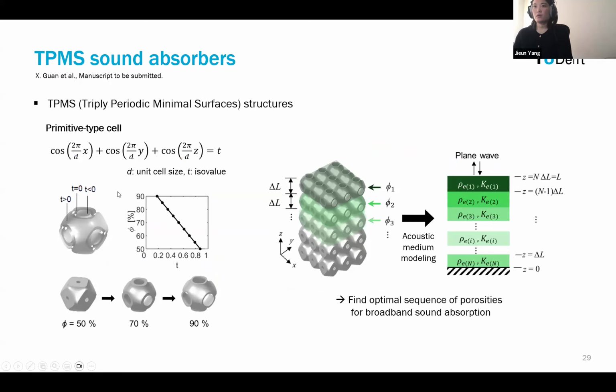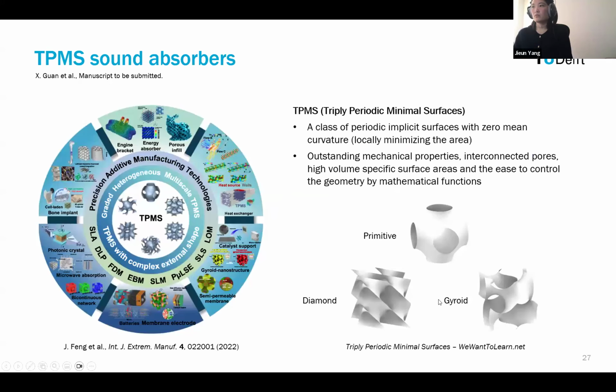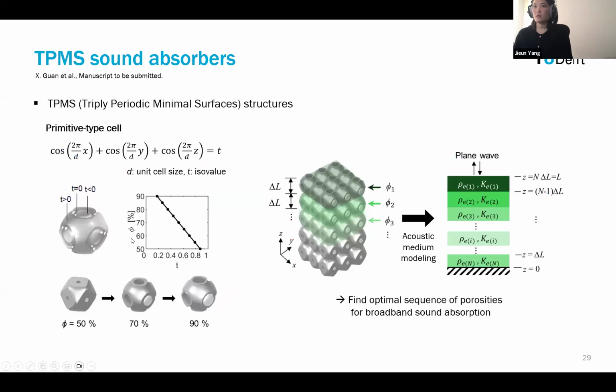So we picked one type of cell. I forgot to mention it in the previous slide, but there are many types of TPMS geometries. Among these, we use this primitive type cell, and the geometry of this cell is expressed by these cosine functions. And D here means the unit cell size, and T is the iso value. So if you change the iso value T, then you can change the porosity of this unit cell. And our final goal was to optimize the porosity profile along the thickness of this porous layer to have broadband sound absorption.